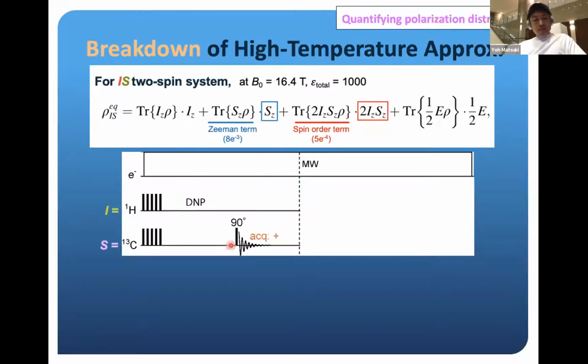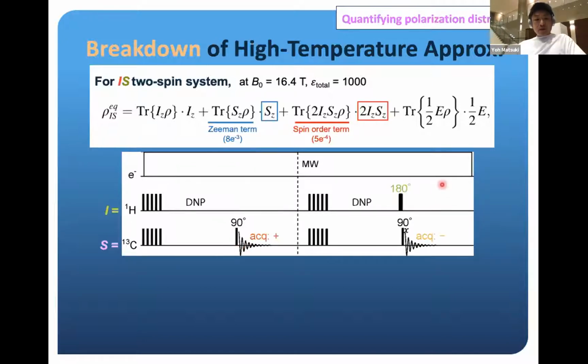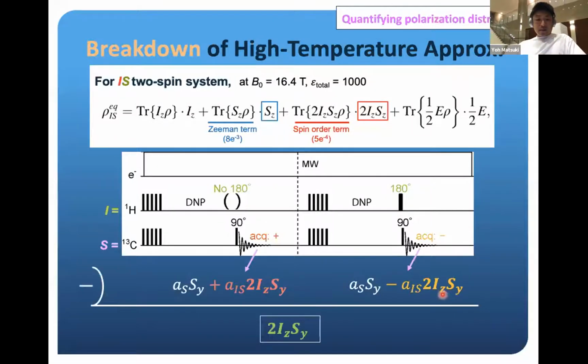So we did this simple experiment where basically we hyperpolarized proton and observed the carbon NMR with a 90-degree pulse. But if you do this 180 pulse on proton in the second experiment, this spin correlated term will be inverted in sign. And by just subtracting these two data sets, the spin correlated term will be selectively observed. That's the idea. And of course, by just adding these two data sets, the Zeeman order term will be selected.